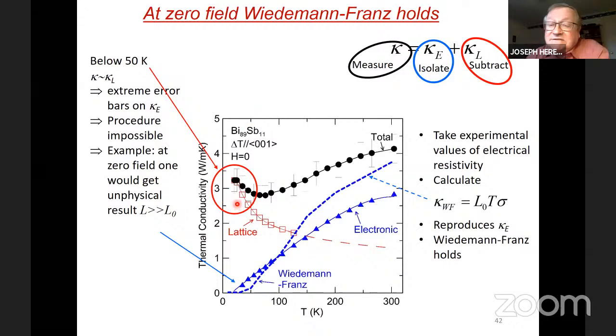Let me show what would happen if we were to force this through a zero field measurement, where we know Wiedemann-Franz holds. Well, the simple straightforward subtraction gives us the blue points. The Wiedemann-Franz law would give us this dashed line. If we were to take the ratio of these two things that are close to zero, we would end up with a number that is much, much larger than L0, but that is completely wrong. That is entirely within the error bar. So this measurement is impossible below 50 Kelvin.